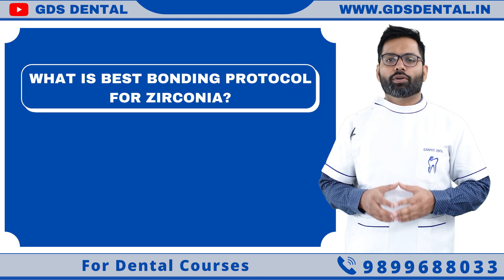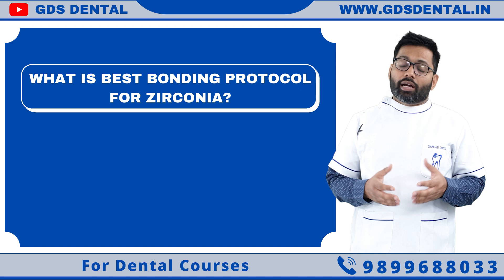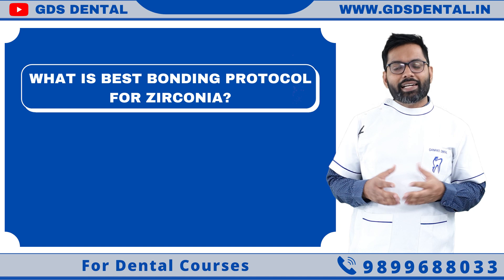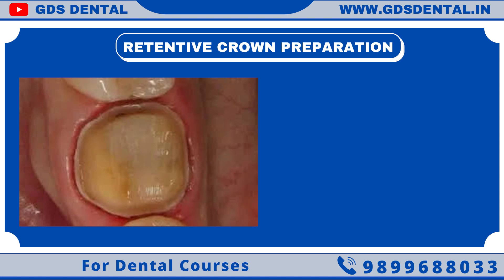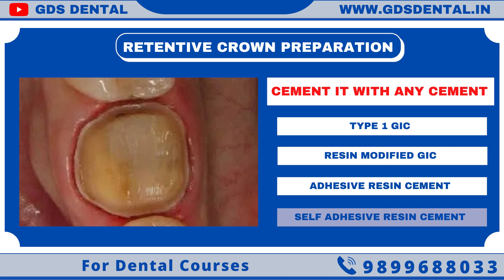When we give a zirconia crown, there can be two types of crowns: a zirconia crown which has retentive features and enough occlusion clearance, and second, a crown with less retentive features. In the first situation, where you have proper retention and conventional tooth preparation with enough occlusion clearance, you can use any cement like type 1 GIC, resin modified GIC, adhesive cement, or self-adhesive cement, and your zirconia crown will last long. In my clinic, in this type of scenario, I use self-adhesive cement as it saves my time.